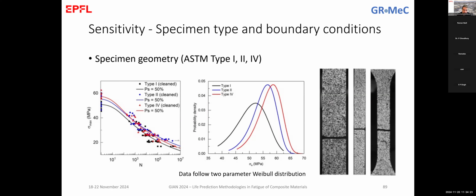And we plotted this in fatigue S-N curves, the stress and the S-N plots. And we did also fit Weibull distributions. And we've seen that there is an obvious and very significant trend to show that type 4 specimens that are shorter and thin are better than type 2 that have the same thickness. So there is no size effects in this case. And both are much better than the specimens of type 1.